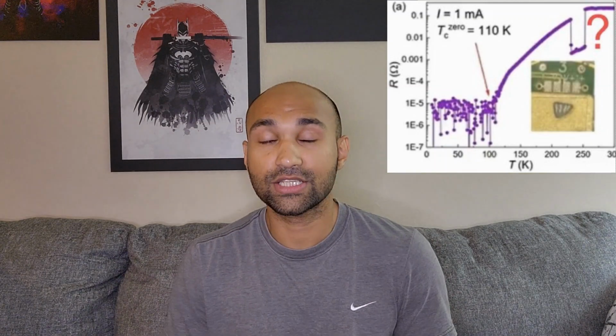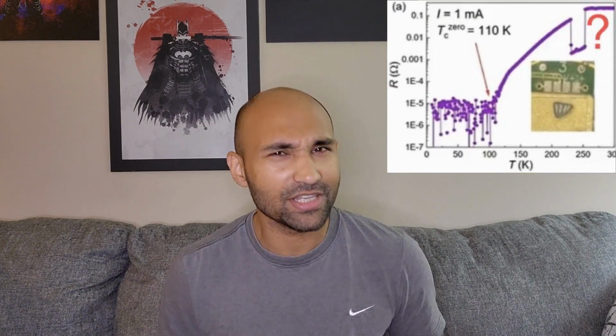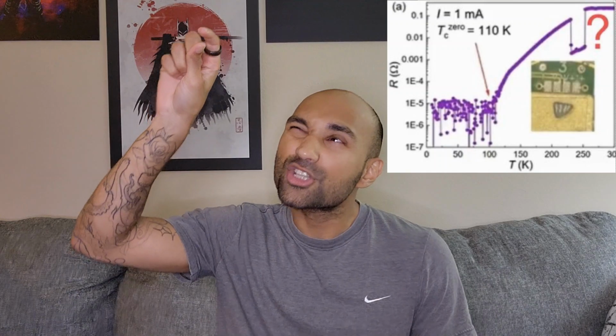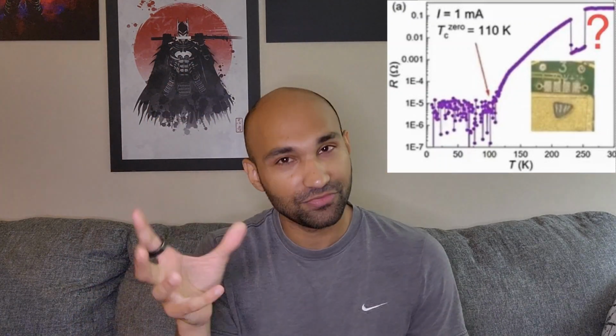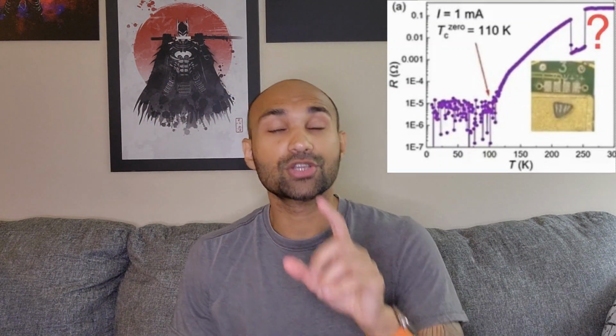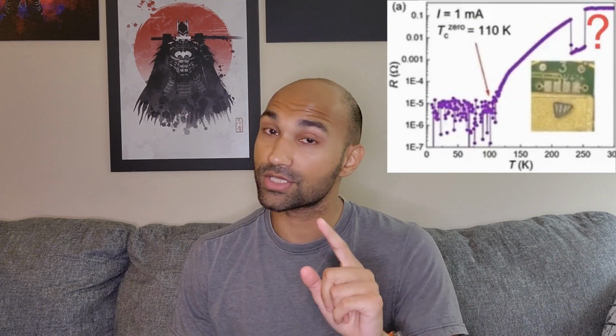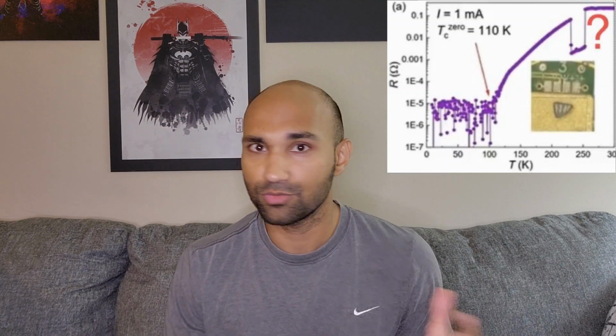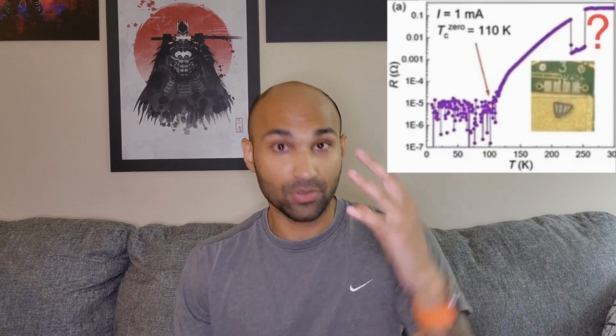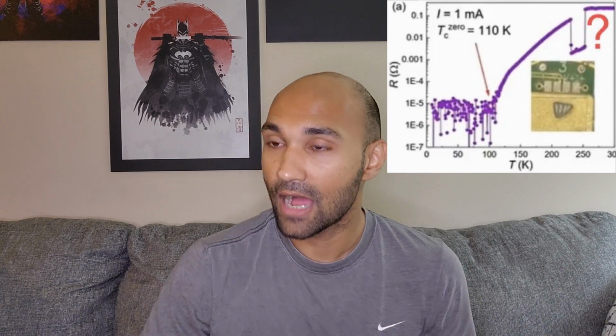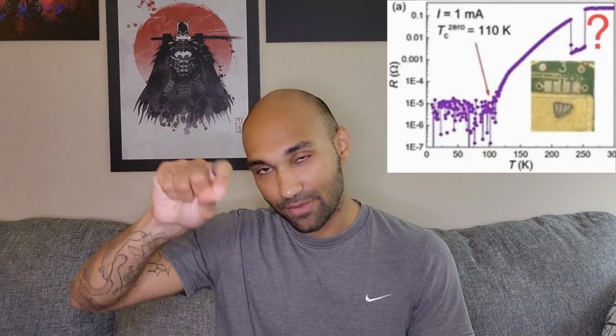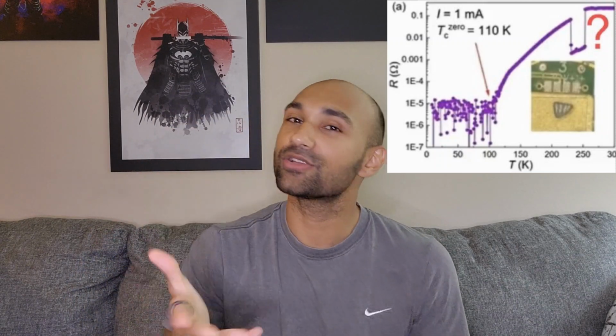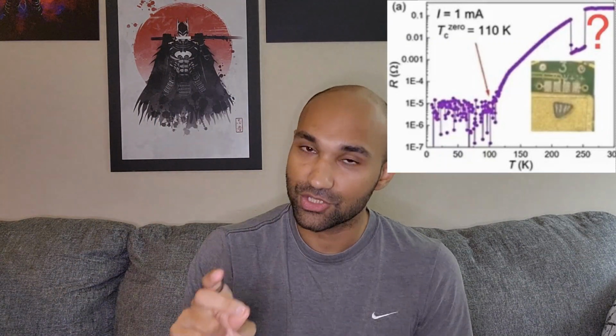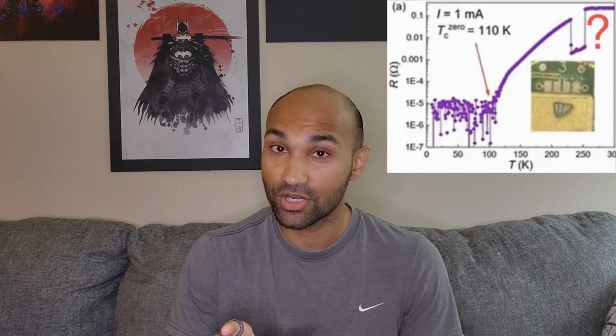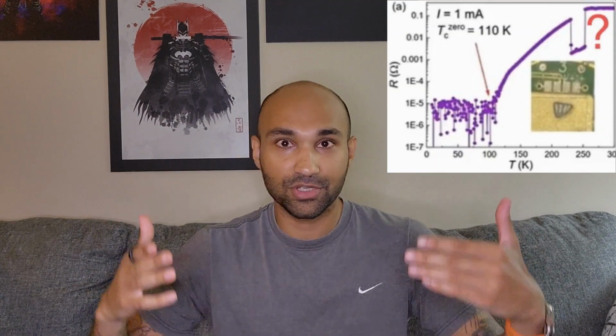If you look at the actual curve that they generated for the resistance measurement, there were a couple of interesting features there. One, there was this weird, sharp, sudden drop at around the 250 Kelvin mark, which wasn't zero resistance. There was almost an order of magnitude plus drop in resistance at around 250 Kelvin, but even if you take that amount of resistance there, it's not near zero. It wasn't superconducting at 250. I just want to clarify that. I saw some posts on Twitter saying that it had a drop to zero at 250.